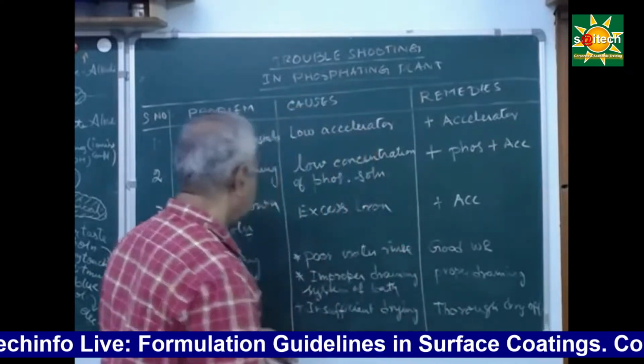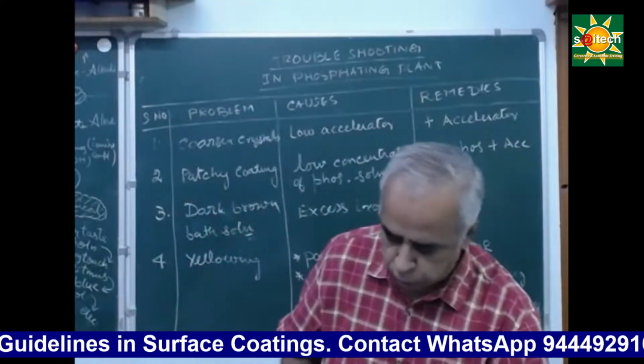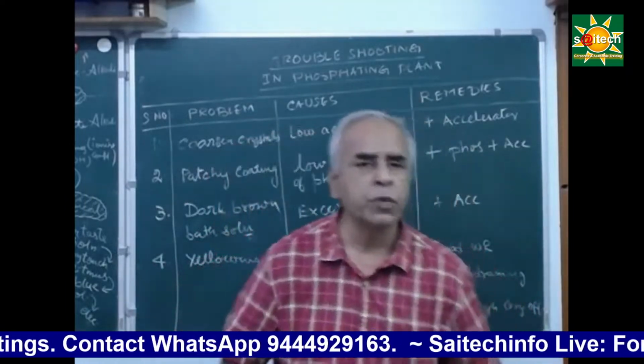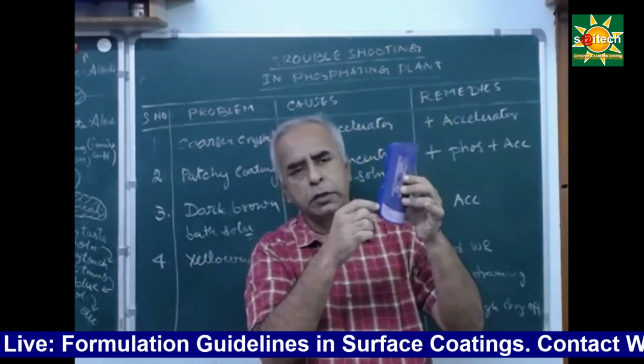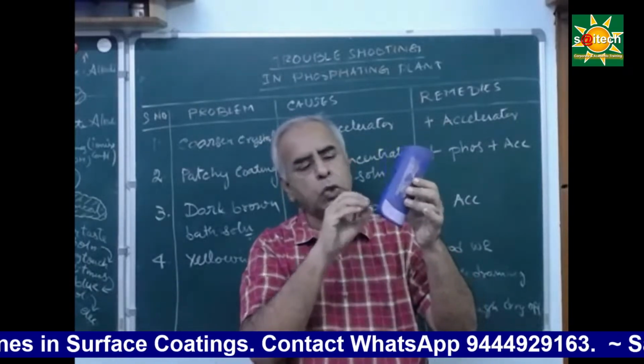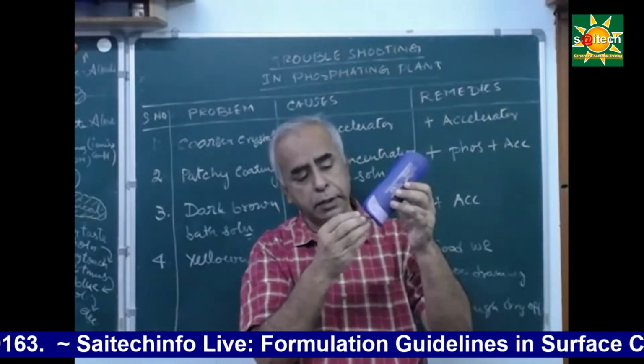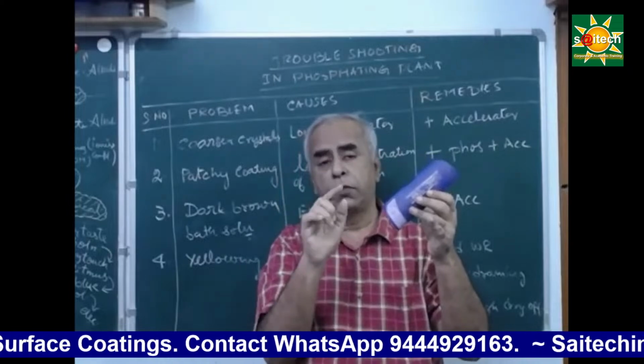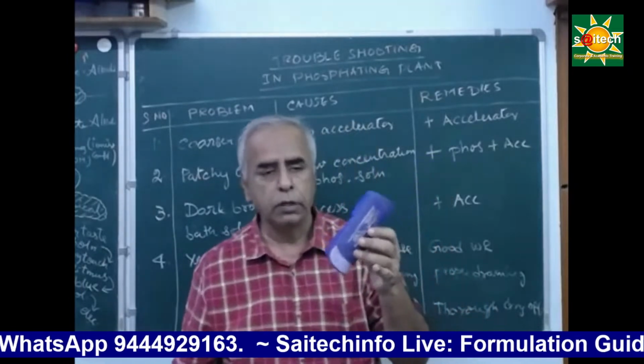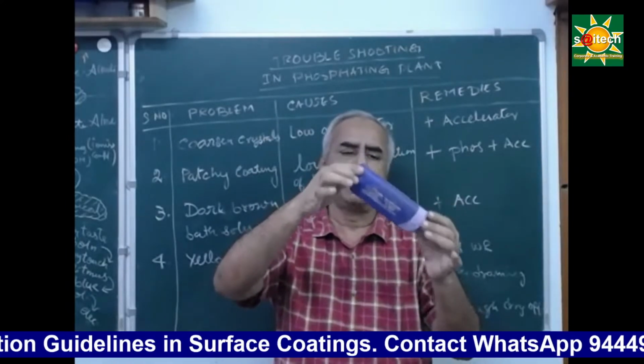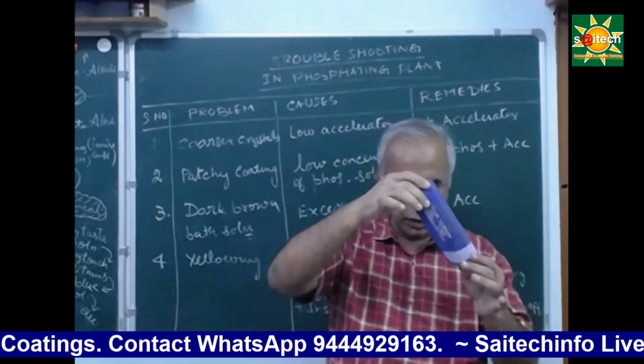Then when you drag out, for instance, assuming that this is the phosphated component, there will be some tricky corners, and sometimes they may catch all these acidic solutions in blind corners. So if it is a trap, probably when it is evaporated, there will be a more concentrated part in that particular blind corner, and that should be properly removed. So in fact you have to take care of the design aspect also. Otherwise you have to make a jig in such a way that all the rinse solution is drained off. So the angle, the orientation of the component should be maintained.